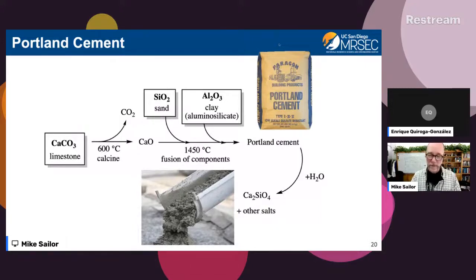So when you take that powder and you mix it with water, as you know, it becomes this sort of sludge that eventually after a few hours will set up into a solid mass. And the chemistry that's doing that is actually making it precipitate. The calcium ion in the calcium oxide is dissolving in water, and the silica is also dissolving in the water and making a product of calcium silicate, which is shown at the bottom of the slide here. And that calcium silicate is a very insoluble form of calcium. Basically, that's the glue that holds concrete together, that holds cement together. So we're going to try to harness this same chemistry in our silicon nanostructures.